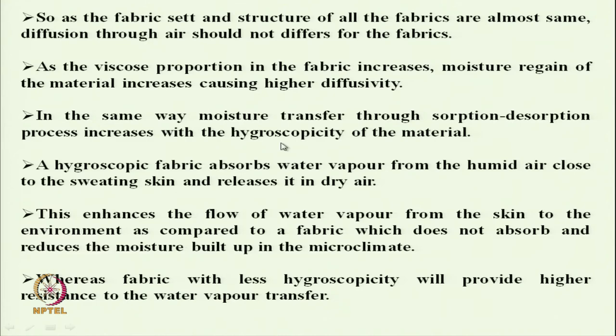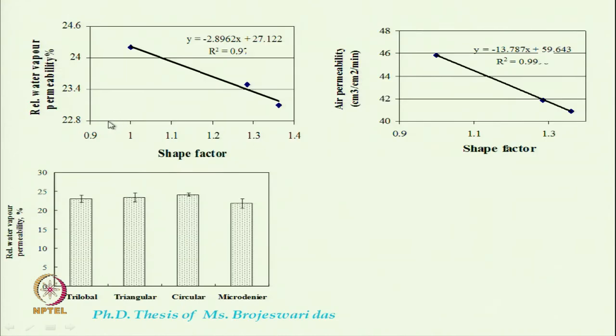So, we have used three different shape factors of polyester: one which is circular, 1.3 which is triangular, so not one, it is around 1.3, and 1.35 which was trilobal. So, these three materials were used, and what has been observed is that with the increase in shape factor, relative water vapor permeability reduces, like air permeability also reduces. So, this is basically due to the air drag.